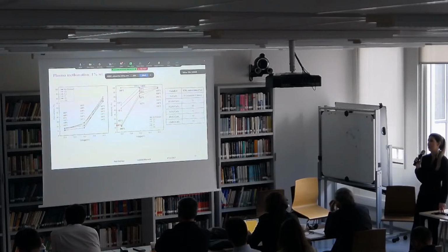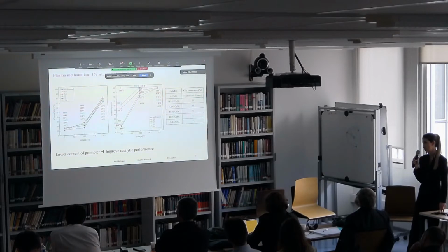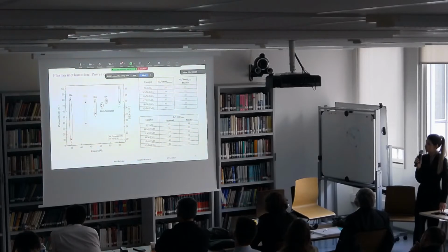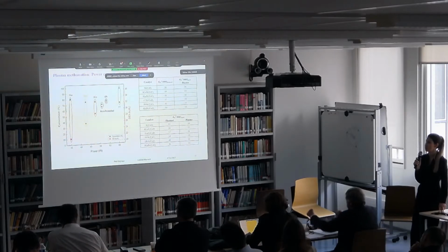Regarding the catalytic performance under plasma condition, it can be seen that, interestingly, this series of promoters with lower loading all have higher CO2 conversion under plasma condition. However, the best catalytic performance goes to the lanthanum-promoted sample with 80% CO2 conversion. It would be interesting to see if this catalyst also has the best performance regarding power consumption. As can be seen, interestingly, lanthanum also has the best catalytic performance regarding power consumption.